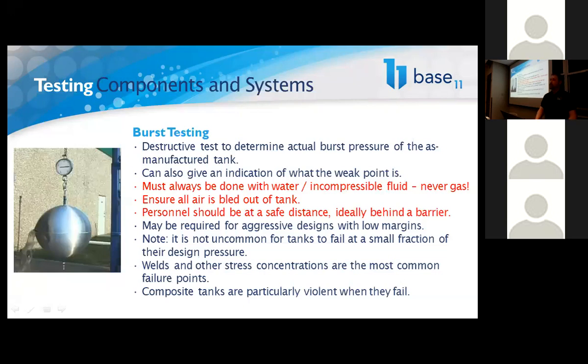So one of the things that we require for the Base 11 challenge is that any pressure vessel with a safety factor of lower than 2 needs to have at least one identical article put through a burst test, so that you can try to substantiate that you're actually getting the safety factor that you intend. And as we mentioned, composite tanks are especially violent when they let go. So you need to be very careful with doing that type of testing.